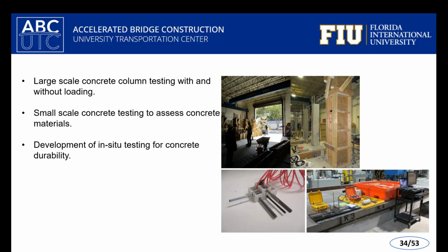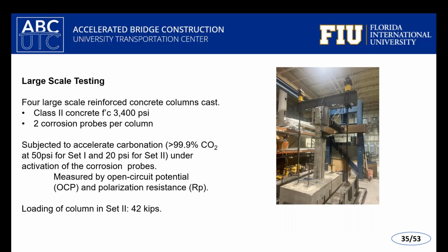bit on those already. Those are the columns that were cast with the initial normal strength concrete in the interior, a fairly benign concrete. The idea is that this type of concrete would probably have more damage than a higher performance concrete, and it may need retrofit. The bottom left-hand corner shows some of the sensors that we fabricated and designed here at FIU and implemented on these test specimens to identify corrosion development, and some of the material testing that went along with part of this research program. So here are some more pictures of the test specimens during testing.